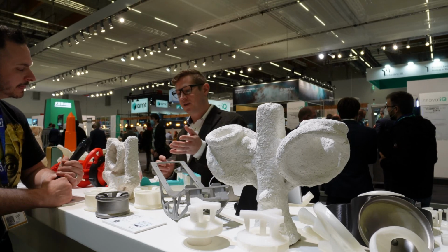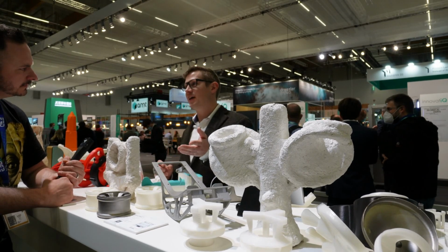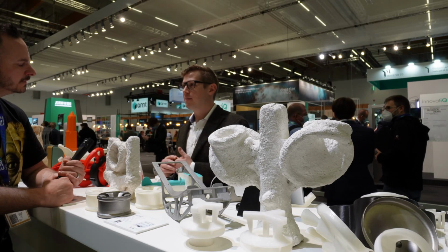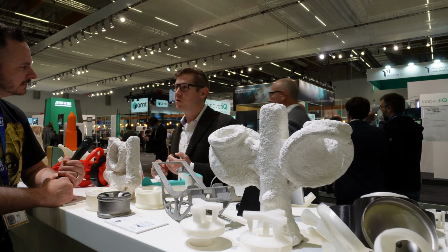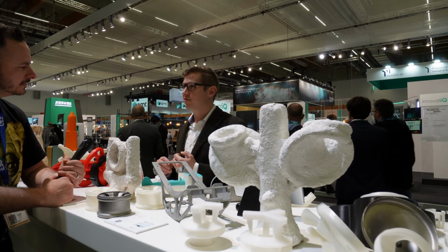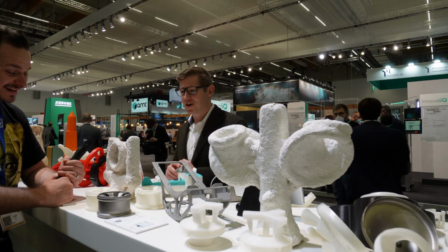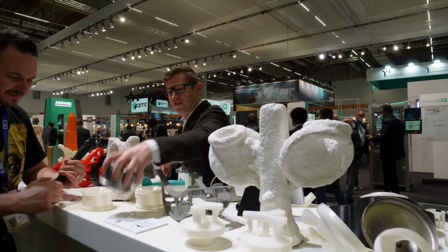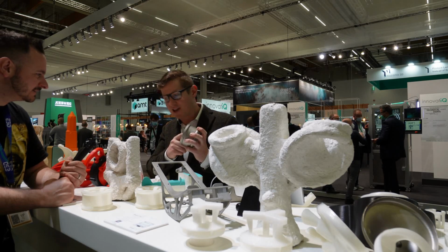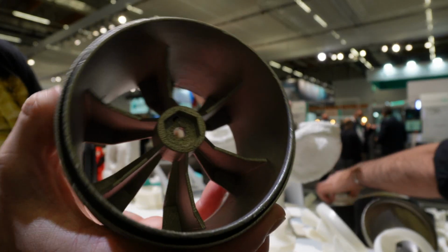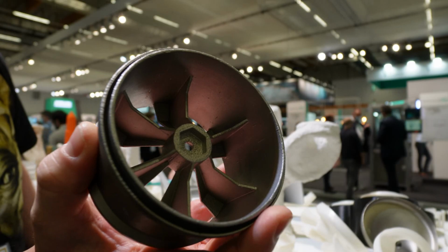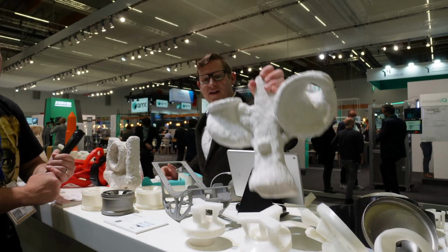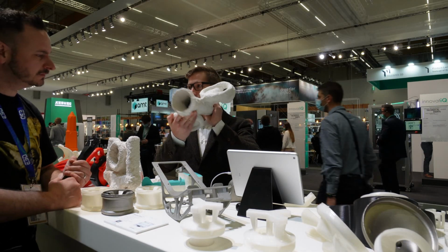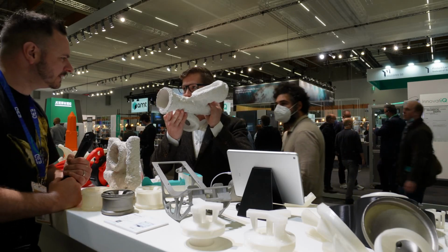Right. So we've developed, the best feature about the Polycast is that it burns away very cleanly, has an ash residue of 0.0003%. Right, okay. And you can see the part here. You can see the layer lines on the inside. So you really keep that detail inside the mold. If you look inside the mold here, you see no residue from the burnout.